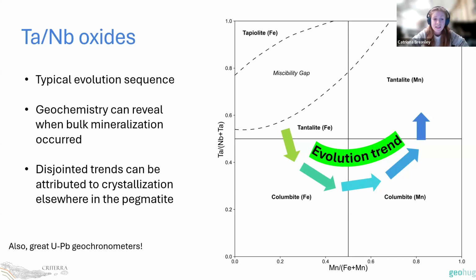However, it's very common to see disjointed trends on this quadrilateral because crystallization of these oxides can be influenced by different minerals crystallizing elsewhere at the same time in the system. For example, garnet is known to buffer the manganese content of the system. And also they're great uranium-lead geochronometers.